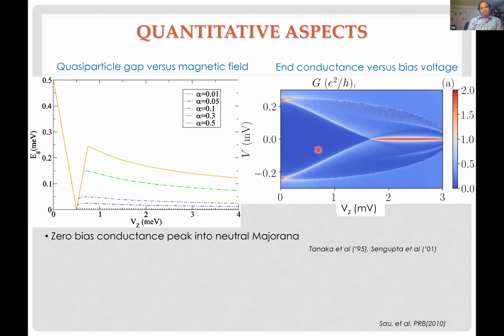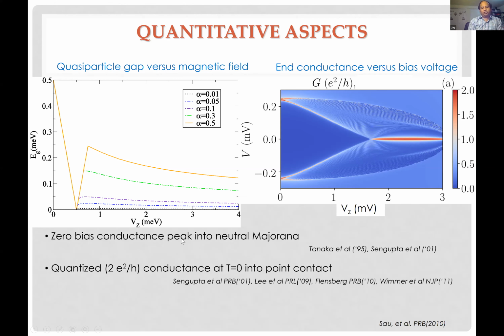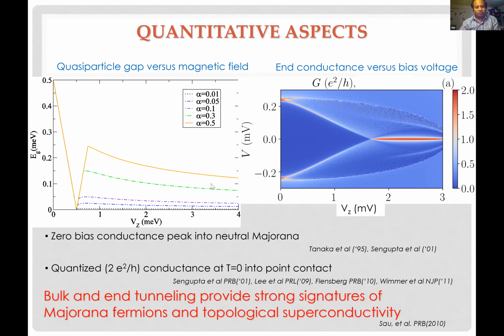This is a little bit unclear. This varies from simulation to simulation, but then I should see a zero bias conductance peak show up. And it turns out that this conductance peak is actually quantized at exactly 2e²/h. And this is actually strange: independent of how high the tunnel barrier is, it's still quantized. So it's a topologically protected quantity. In principle, if we saw both of these coming together, this would be a good signature that people would believe. At least I think.